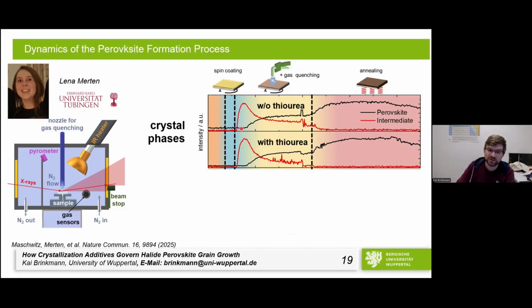So I put this in a little bit of a more direct representation. In black, you see the perovskite. In red, you see the intermediate. So I think this is basically the thing that happens between a perovskite and the liquid phase. So you have like a solvent complex intermediate. And the interesting part is that already during the gas quenching, we have a significant amount of perovskite actually appearing. So we have not a pure intermediate.